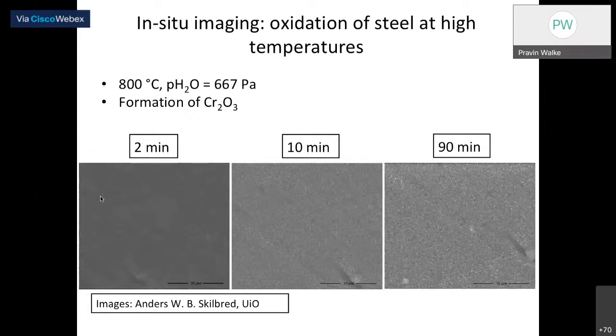And then how that steel gets oxidized with temperature and time has been seen in these images. After 2 minutes, you find very few small white spots. After 10 minutes, there is an increase of white spots. And after 90 minutes, 1.5 hours, nice white grains have formed on these surfaces. So the oxidation rate is improved and formation of Cr2O3 is also possible, right? This is how we can do in situ topographical measurements using this SEM.